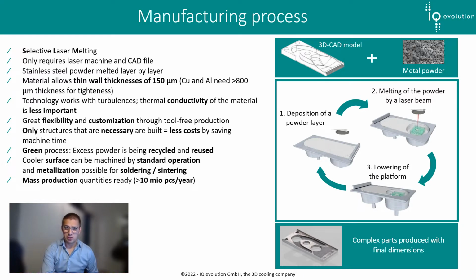We often hear the question, can you do this with aluminum or copper? And the answer is, we focus on stainless steel because the wall thicknesses we can reach are only 150 micrometers, while with copper and aluminum you would have at least 800 micrometers and need different laser machines and more machining time, making the whole process more expensive.